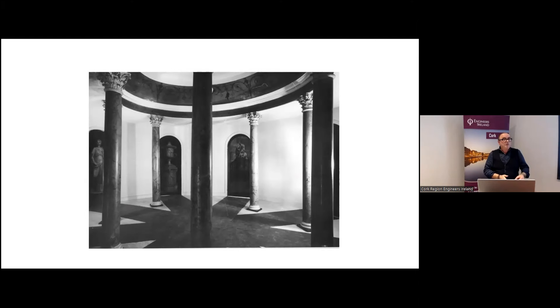What you actually find with rammed earth — we finished ramming probably in August or September, and we've been observing it since. On a hot day you can get a bit of dust loss and it looks drier. But on a wet day, it almost strengthens itself with moisture. Once you get your moisture content reasonably correct during construction, there's a curing process with the cement, and thereafter the wall reacts very well to moisture — it almost likes living in a wet environment. It's been nearly a year and a half now and it's really solid. I actually anticipated more erosion on the wall — so far so good.